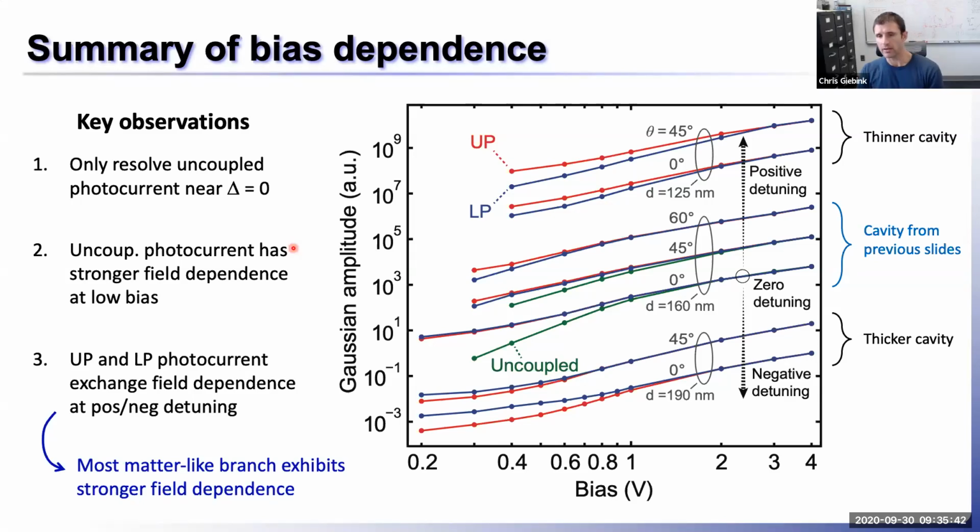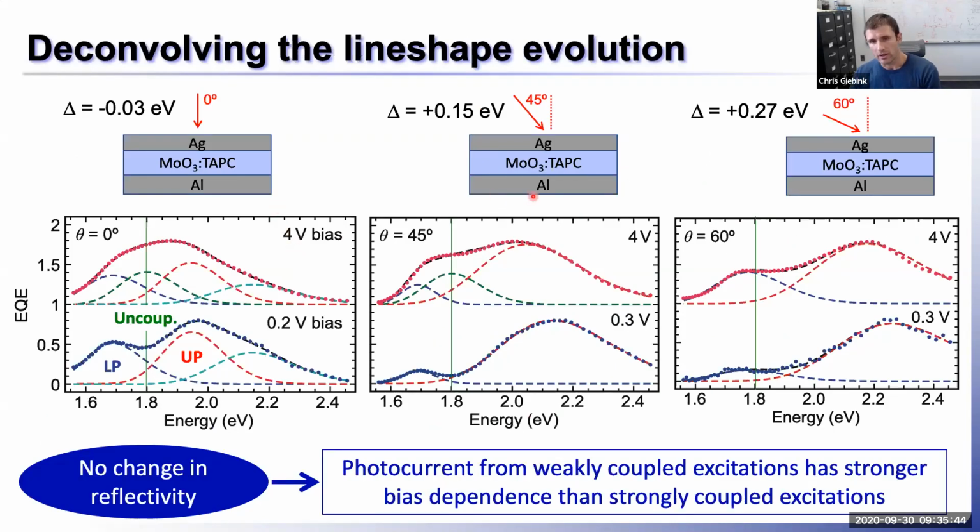Yeah, so that's an important point. The fabrication of the devices is all by thermal evaporation. So we thermally evaporate the aluminum and then co-evaporate the TAPC together with the moly oxide and then the silver mirror on top. Because they're very highly doped films, you get a lot of dark current, period, which is problematic when trying to measure the photocurrent very sensitively.